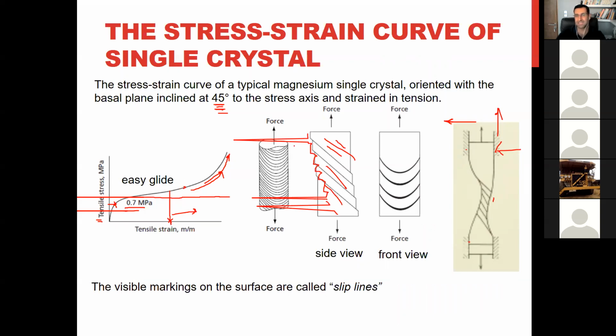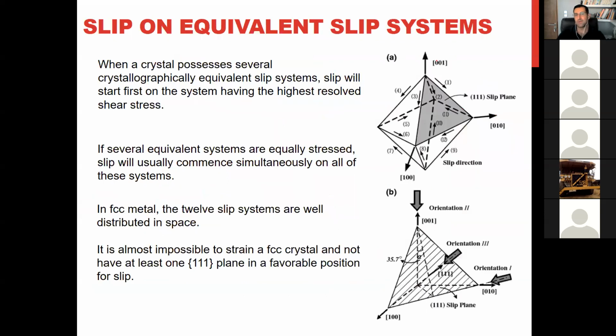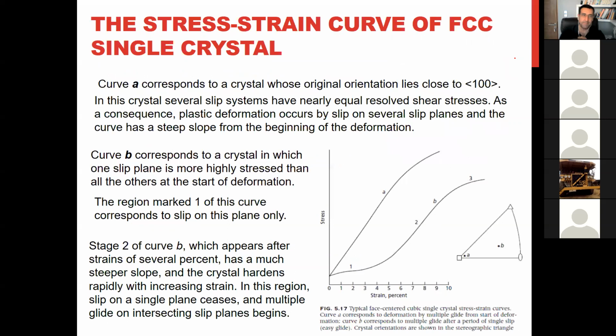Nothing happened, just practically, as we cannot adjust the fixtures of our equipment, we see this part is going up. But in the case of FCC, if you are applying load in this direction, imagine you have a sample like this, a single crystal FCC, and this direction is 100. It means at the same time you are activating several slip systems together, okay? What will happen? So let's see.